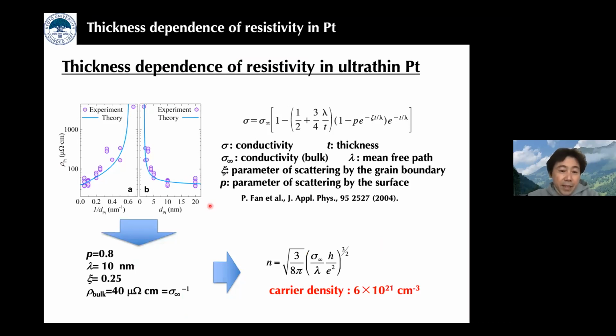First, I show the thickness dependence of the resistivity of platinum. As you see, when the thickness of the platinum goes down, the resistivity of platinum monotonically increases and becomes very, very resistive. This is due to grain boundary scattering, surface scattering, and so on. But this behavior can be theoretically fitted by using this fitting function, and from the fitting, we can extract some physical parameters. The most important parameter in this work is the carrier density.